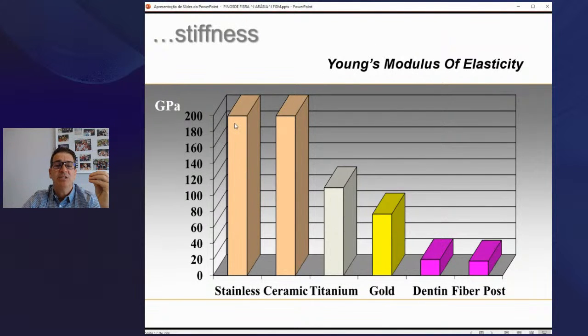For example, if you look at stainless steel or ceramic, the Young's modulus of elasticity, the stiffness, is extremely high, 200 gigapascals. If you look at gold, which is better, but not many people use it, it's about 70. So we have better, but look at the dentin, 20 gigapascals. So we have a huge difference between metallics, ceramics, and dentin. That explains why there's so much transfer of stress to the apical part. The first fiber posts used to have 20 gigapascals. But because of the cementation problems, now they are not that flexible. They are a little bit more stiff because they need not to debond from the tooth.